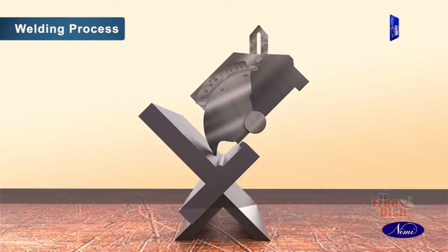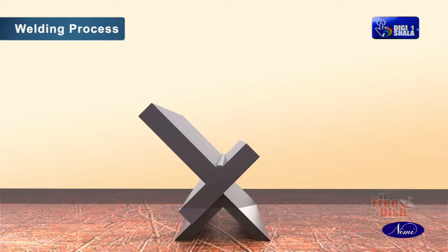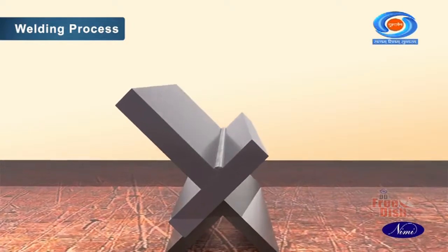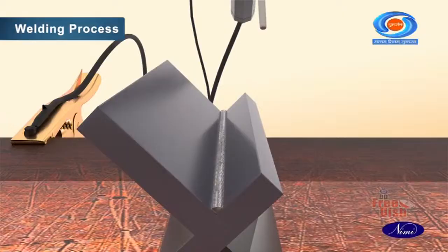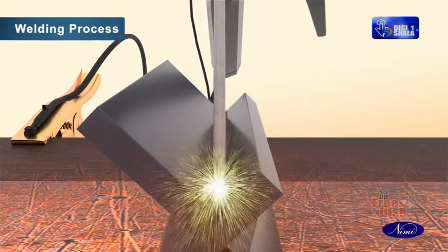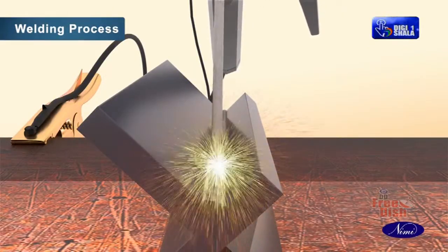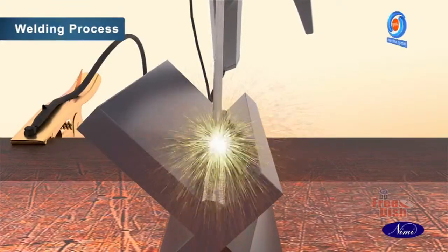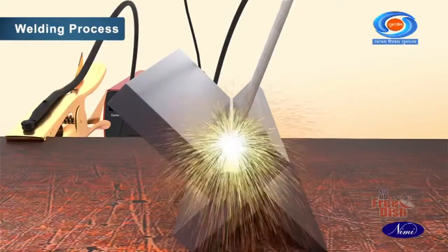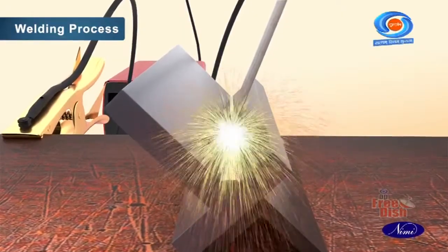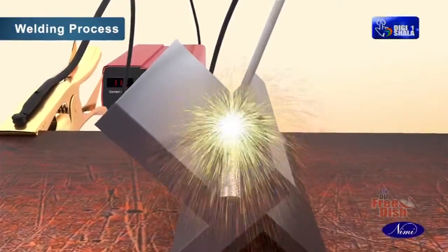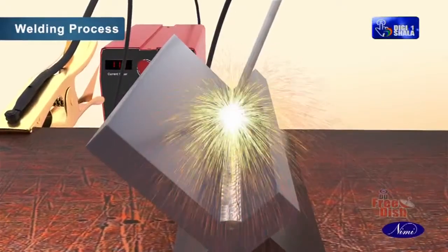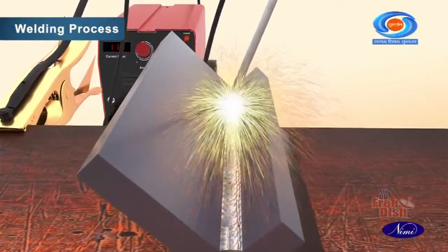Use a weld gauge for checking the leg size of the weld. If you do not get the required 10 mm leg length in 2 runs of weld deposit, then deposit a third run using the same technique adopted for the second run. Stop the electrode weaving for a moment at the toes of the weld to avoid undercut. Fill the crater at the end of the bead.